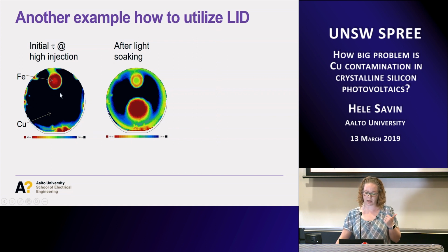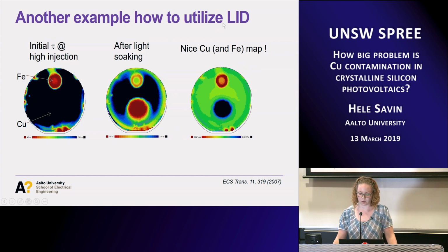Now the good thing is that at high injection, the iron-boron pairs will break up, and in the end you have an increase in your lifetime in this area. So if you have iron contamination, your lifetime goes up. If you have copper contamination, your lifetime goes down. So if you subtract these two maps from each other, you can clearly separate them, and see which direction the degradation went. So with the same measurement, you can measure both the iron and copper map, because the change was either positive or negative.